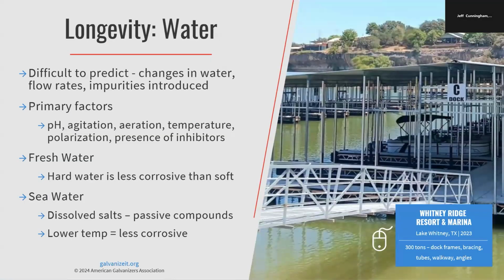Water is also difficult to predict, similar to soil. There are changes in water flow rates, impurities introduced. Primary factors are similar to the soil: pH level, agitation, aeration, temperature, polarization, and any presence of inhibitors. With fresh water, a good rule of thumb is hard water is going to be a little less corrosive than soft, because of the added chemicals in soft. With seawater, you want to look at dissolved salts and passive compounds, and a good rule of thumb is lower the temp, less corrosive. We have a whole marine and water page on our website with all of our examples. We're seeing more docks and marinas being built out of galvanized steel because it does well with water.